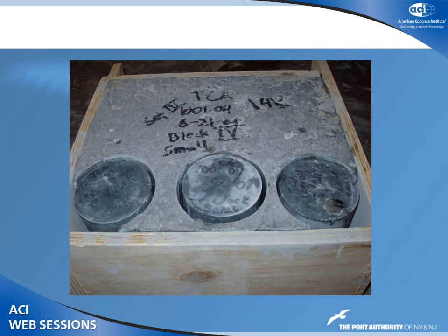So here's the slab. Okay, and what we did in addition to that, we said let's put some cylinders in these slabs also. Okay, so that will be a control. In other words, these cylinders will be curing at the same temperature, and then we'll test these and we'll see how these compare to the cores. Not that we knew where we were going, but that's what we did. Okay, but anyway, these slabs were cast, and some of them were cured. I'll show you. Some of them were cured in the lab, not moisture, just at lab conditions. Others were cured in the moisture.